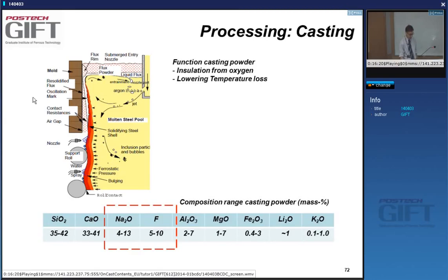But by the time you leave the mold, the steel is by no means fully solidified. There's still a lot of liquid steel inside, and so in between the support rolls and the bending rolls, the ferrostatic pressure will deform the surface of the material. So you'll have some bulging. That's why in between there's a lot of cooling, to accelerate the cooling here.